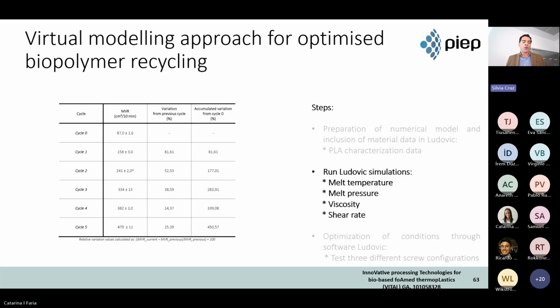So we pick the materials, we run different mechanical characterization. Here we only put the MFR results, because we previously had an indication that the material is getting more fluid, and actually we can see that in the table. So we see a major increase in the values of MVR with increasing reprocessing of the material. It was expected. I would say it was not so expected, or at least not so extreme, as we get in the results. So this led immediately to an approach of changing the screw configuration.